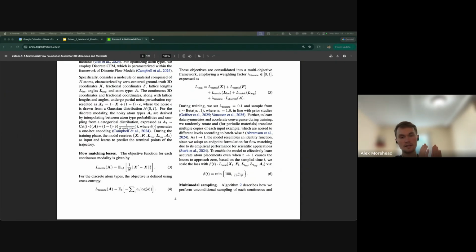So most of the training is happening where we bias the sampling of time steps to the 0.8 and higher time steps, where 1.0 is the clean time step, and 0.8 is pretty close to clean, but not entirely clean. So most of the training is spent near the last part of the time steps, because you can make the argument that for those types of data, like molecular materials, if it's not close to the terminal state, close to the data distribution, it's kind of meaningless and chemically invalid. So there's no use really spending too many flops trying to learn good representations of completely corrupted chemical systems.